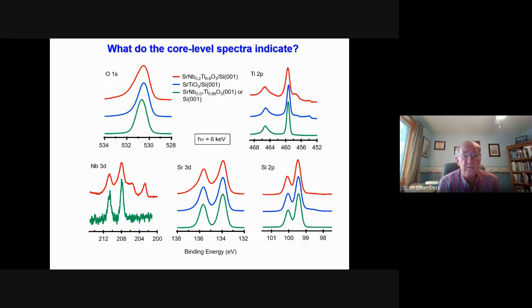And so here I show you three different materials: plain, just undoped STO on silicon, 20% niobium-doped STO on silicon, and then reference flat band specimens of either pure STO with a little bit of niobium, or silicon. Now, notice, first of all, that in the case of the titanium 2p spectra, you have a whole bunch of structure on the low binding energy side for the films on silicon that you do not see on bulk STO, shown in green at the bottom. This indicates a range of valences, 3, 2, 1, and 0. If you take a look at the niobium, you see the same thing. You see a bunch of intensity on the low binding energy side that indicates reduced valences.